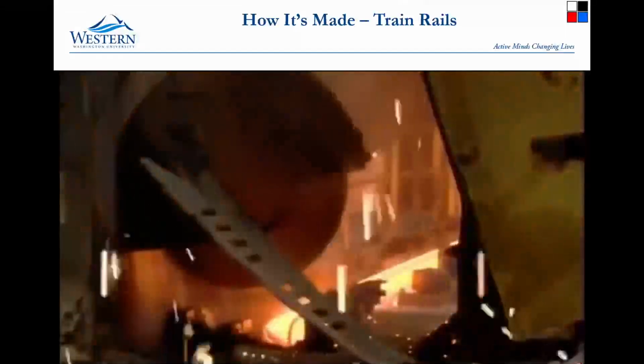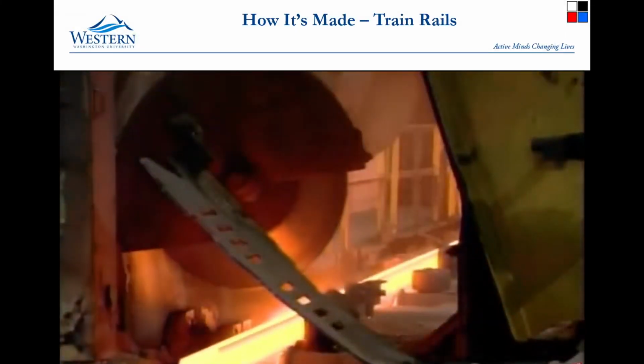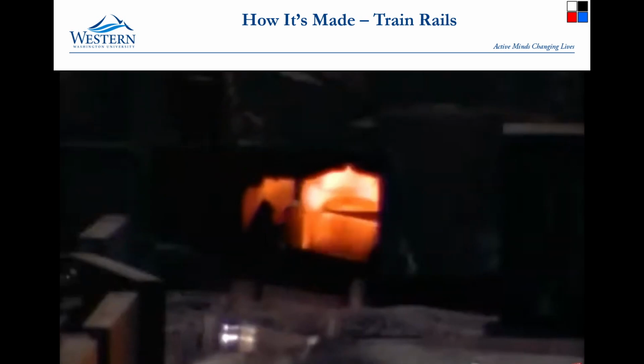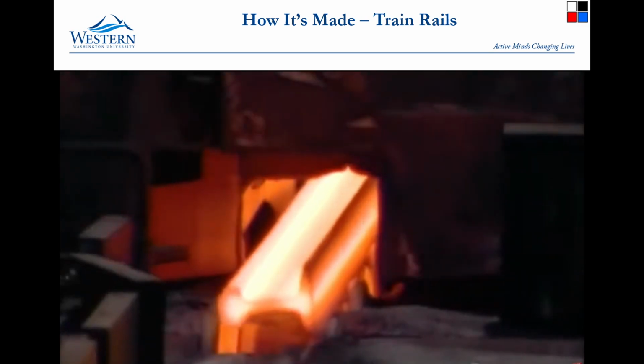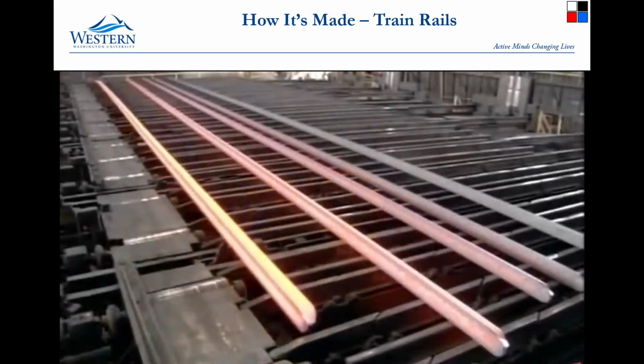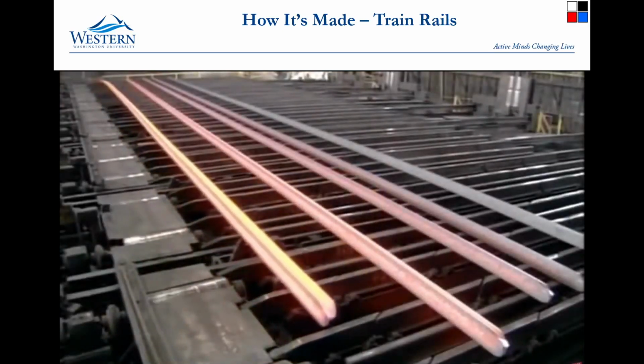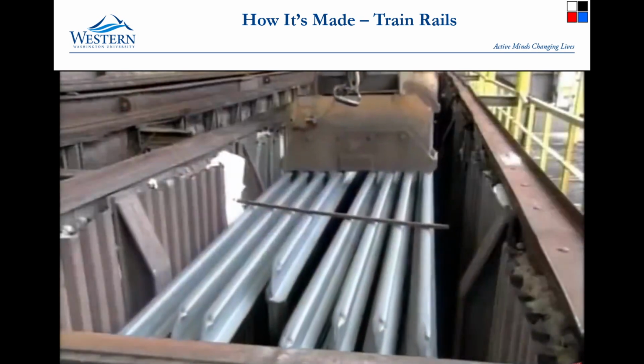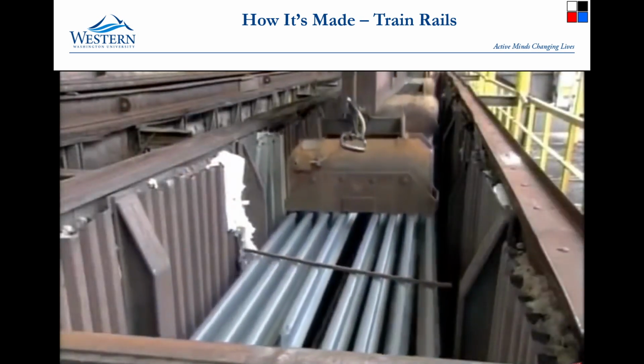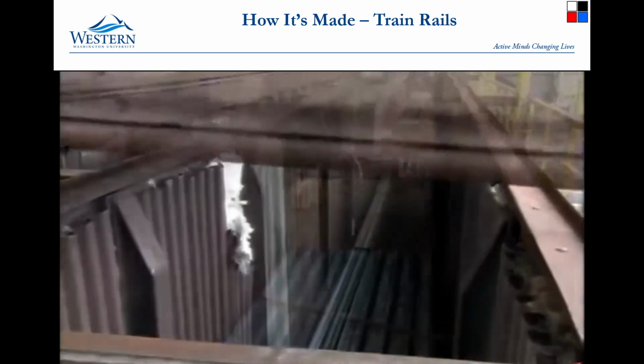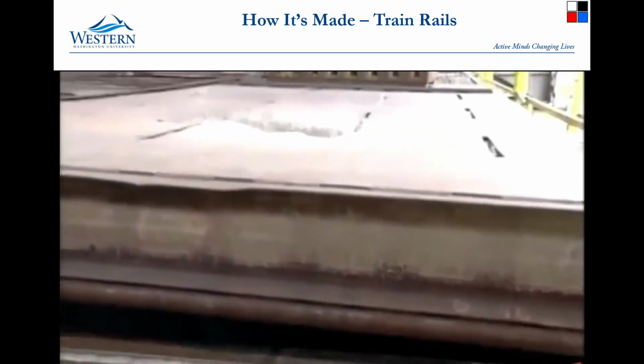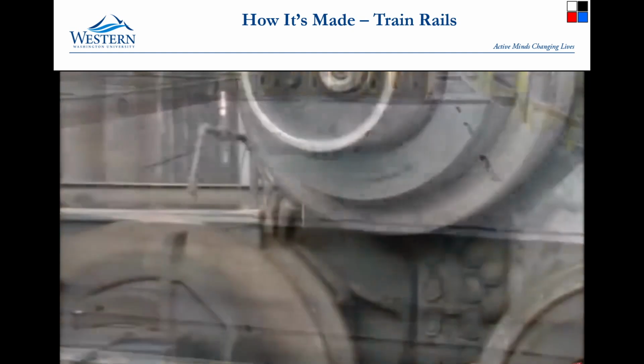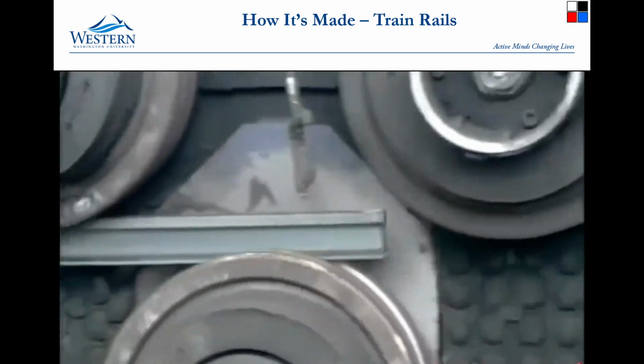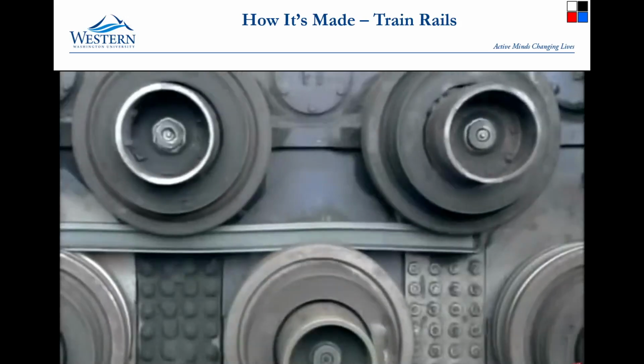For the final shaping, each steel rail passes several times through 3 consecutive mills. This is what a mill's rollers look like. And here's the standard T-shape to which they form the steel. Next, a saw slices off about 30 centimeters to square off the ends. The cut-off pieces go back to the scrapyard. Meanwhile, the rails are laid out until they cool to about 500 degrees Celsius. Then an electromagnet piles them in a holding box, where they sit for 10 hours until they cool to about 90 degrees Celsius. When they come out of the box, they run through 2 sets of rollers. The first set flexes the rail vertically.